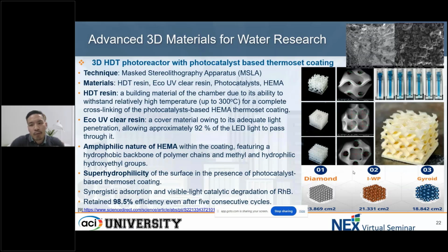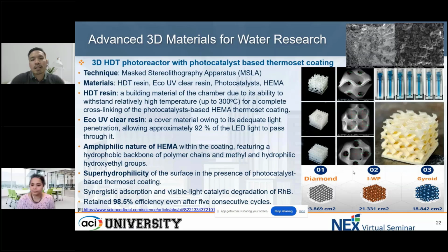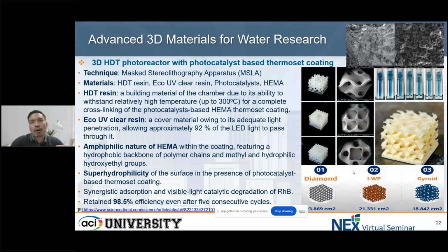Based on what we see, the gyroid, which is number 3, has a specific area of only about 18.84 cm²/cm³, but the performance is much better compared to the other designs. Something quite interesting is that, when we see this result, maybe it is because of something that we have not optimized, which is the water permeability. So we assume that the water permeability of the gyroid shape is much better than the diamond and IWP, even though the surface area is not high.